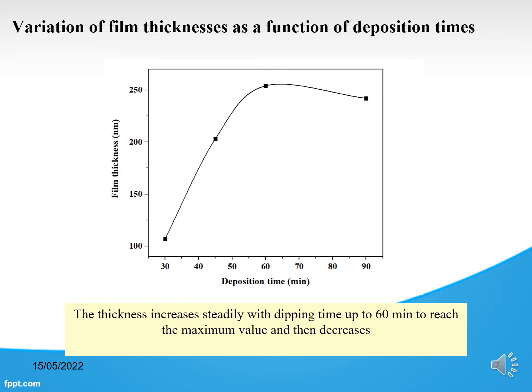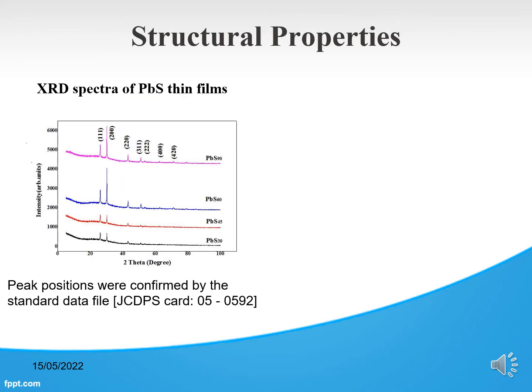The variation of film thicknesses as a function of deposition times. We see that the thickness increases steadily with dipping time up to 60 minutes to reach the maximum value and then decreases. The structural properties, the diffraction spectra of PbS thin films. The peak positions were confirmed by the standard data file.